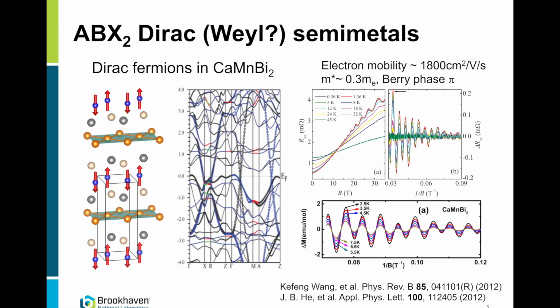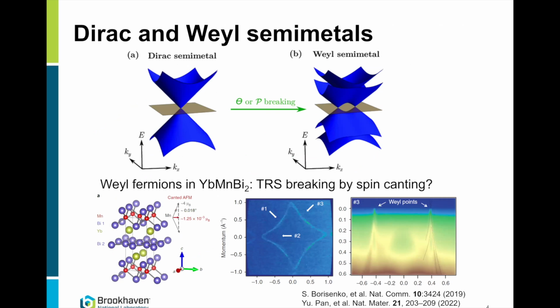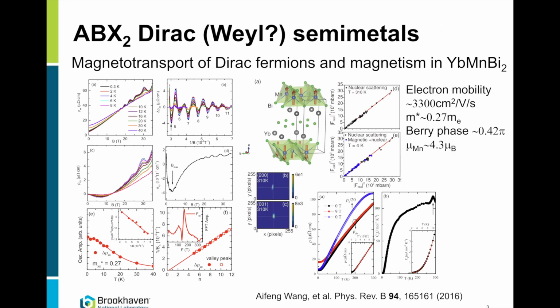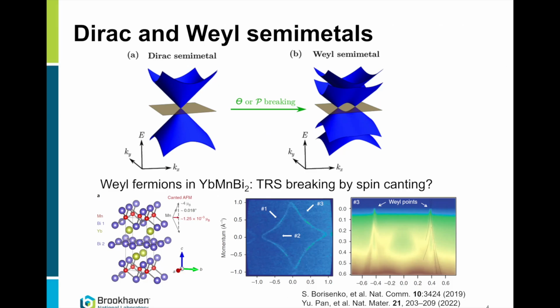manganese ions. The most widely considered tuning is converting a Dirac semimetal into a Weyl semimetal, where the spin degenerate Dirac cone is split into two Weyl cones, and this can be done by time reversal symmetry breaking, such as associated with a homogeneous magnetic moment, which can arise from spin canting in magnetic layers. Normally, neutron scattering gives us a structure which is collinear with magnetic moments along the c-axis, in the interlayer direction. But if this were slightly canted, then that could lead to splitting of a Dirac cone into two Weyl cones.